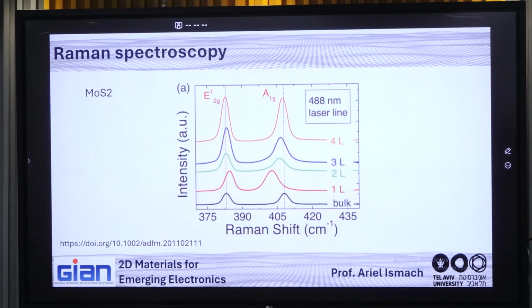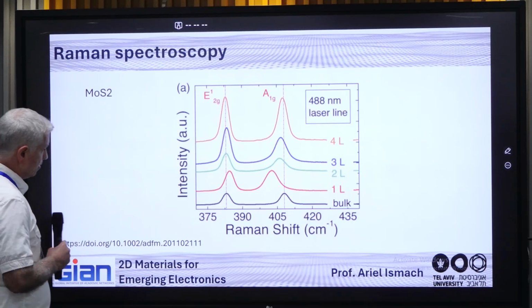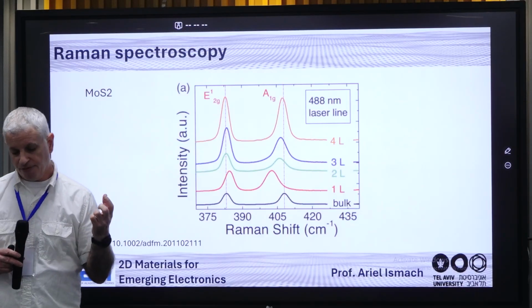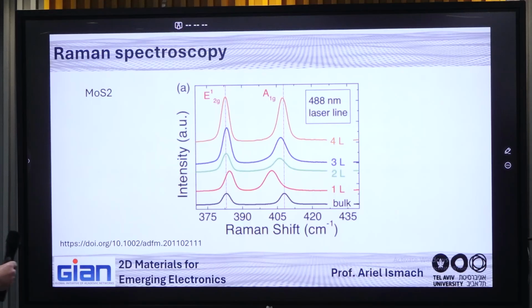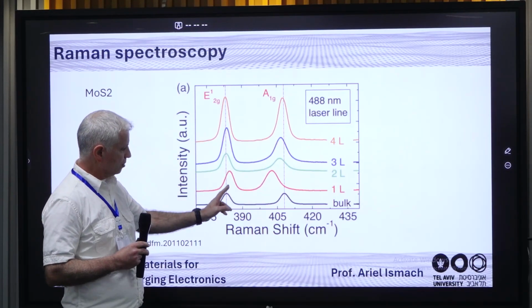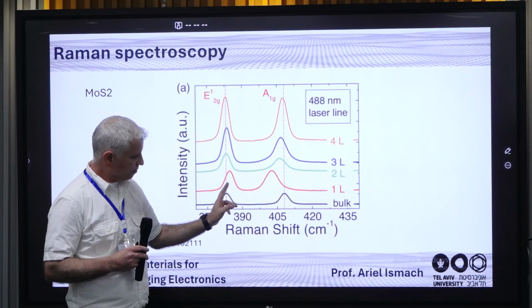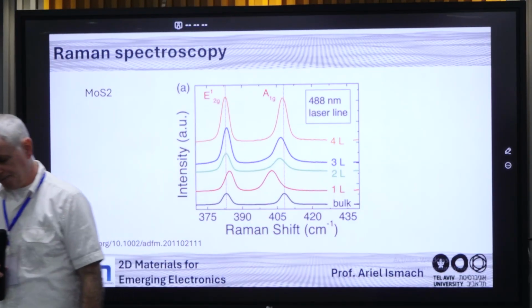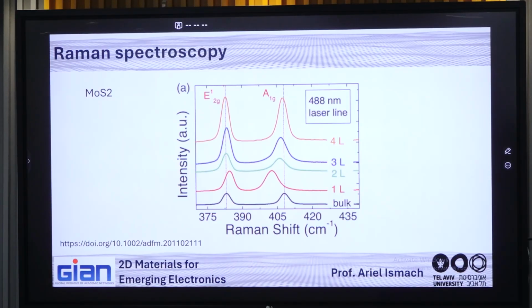Okay, so what about other methods, of course? Raman is a classical, very good tool, and for other materials it's also useful, maybe not as useful as for graphite materials, but it's very useful as well. And here you can see the Raman spectrum for MoS2 as a function of number of layers again. You can see that there are differences, not a lot of difference like we saw earlier, but one characteristic feature of a single layer MoS2, for example, is that the difference between the peak positions of the E2g and the A1g in MoS2 gets lower than 20 cm^-1 for a single layer. So this is a proof that you have a single layer.